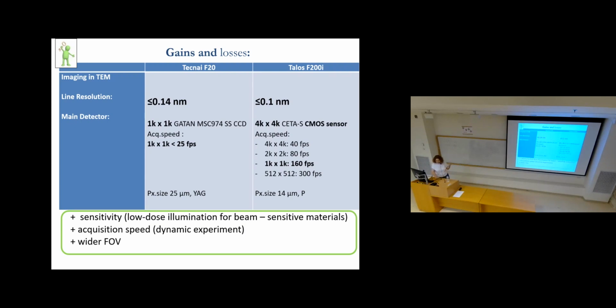What we had was a 1K by 1K YAG slow scan charge coupled device from Gatan. I would say it was advanced 25 years ago. The maximum speed of this acquisition was only less than 25 frames per second, and the pixel size was 25 microns. So we had quite a small field of view, a slow detector, and its sensitivity was not high enough to apply, for example, low-dose imaging. With the new instrument, we have a CETA CMOS sensor, 4K by 4K camera, with quite impressive acquisition speed, small pixel and highly sensitive phosphor coating. So what we add with these abilities is sensitivity, acquisition speed and a wider field of view on top of higher resolution.